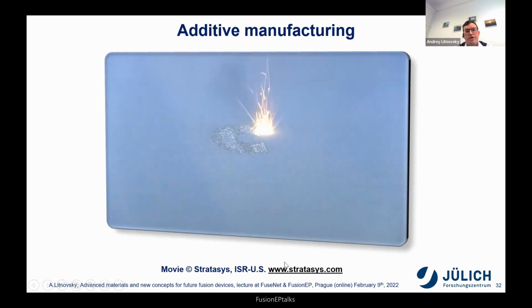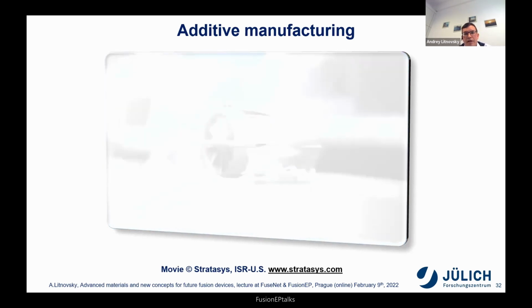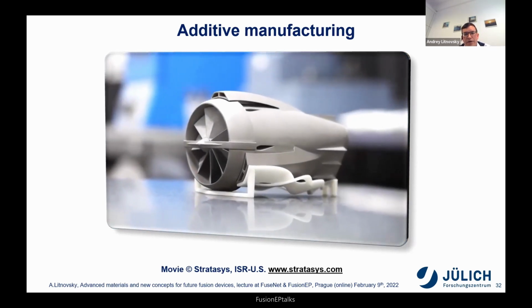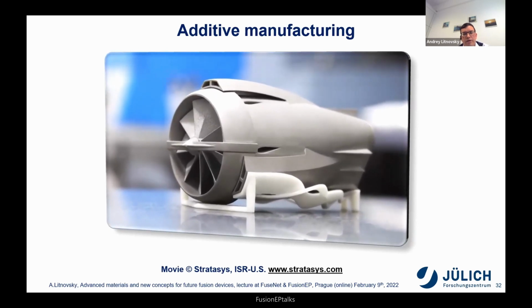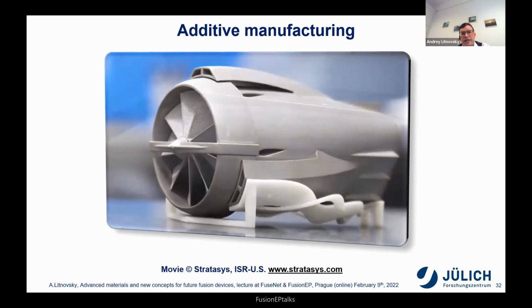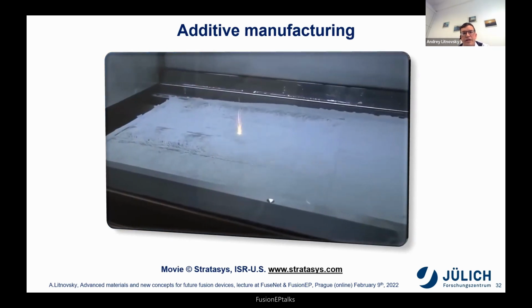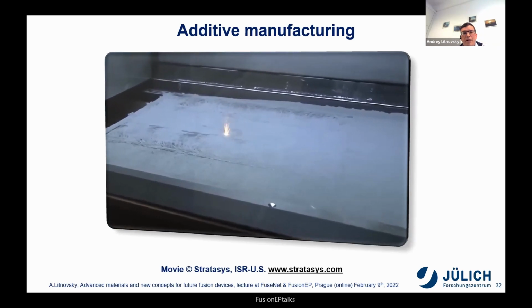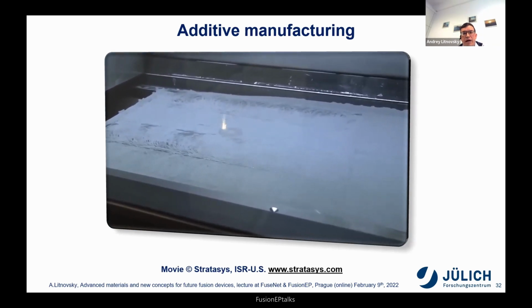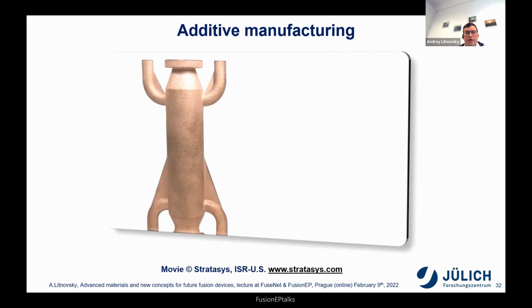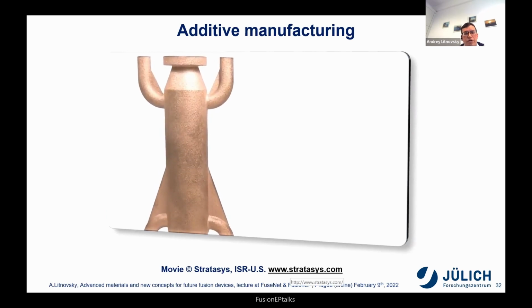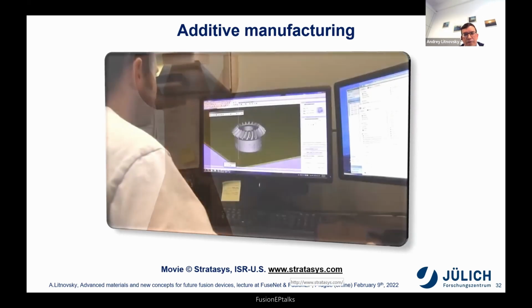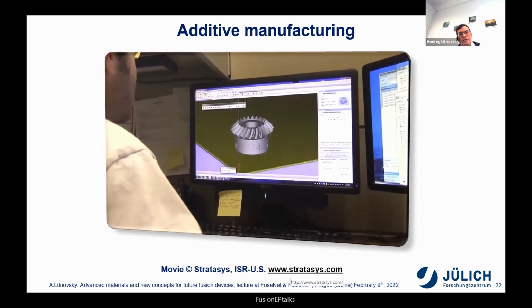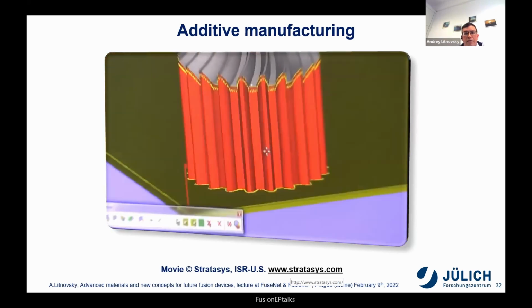We use the energy of the laser or electron beam, which is sintering the powder. So you basically see the powder bed in which this laser is focused. And you see how precisely it can actually melt the powder particles this way, which allows the creation of shapes which you would never be able to sinter with a one-step process.